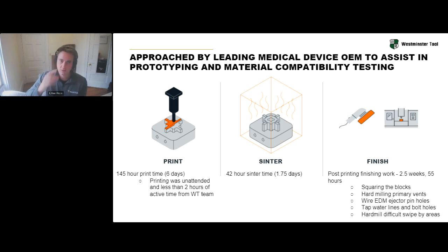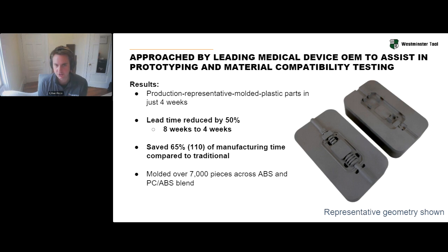The result, they were able to deliver to their customer production representative molded plastic parts in just 4 weeks, which their customer was ecstatic with. They reduced the lead time by 50%. They estimated they would have taken about 8 weeks to build this tool traditionally, and they saved 65% of the toolmaker manufacturing time to produce this, which was really important for them because it meant their toolmakers could spend time working on other things while the machine was printing, and they just had to do a little bit of finishing. They molded over 7,000 pieces across ABS and a PC ABS blend.